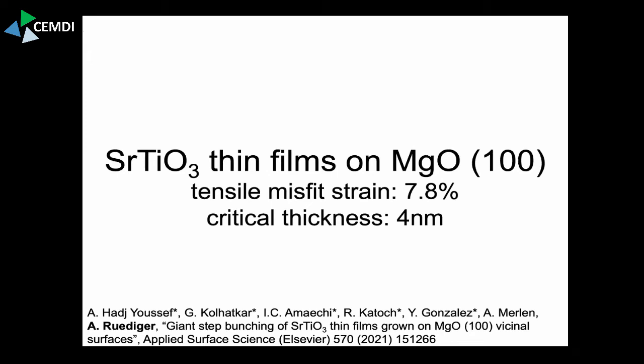The next point was, can we do this in a little bit less violent way? Instead of poking holes into the sample, can we grow this on a film? What we do here is a bit like playing with Legos. We take one Lego layer with the original Legos you buy in a store, and then you build a second layer of Legos on top with those that you would buy on unofficial websites that are not quite Lego. They look like them, but they're slightly different in size. So you can squeeze them on, but it takes a bit of force because they don't have quite the exact size. So this is the mismatch that we have.